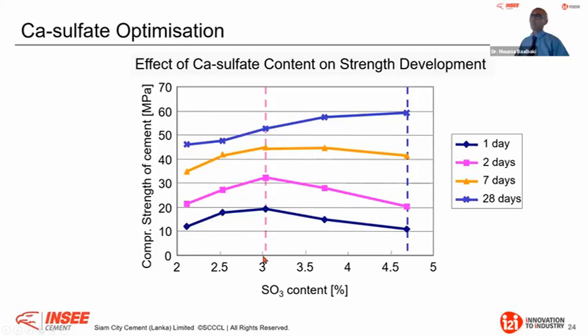But if we don't put enough sulfate, this could be okay for the 1 day strength, but you see the problem we have at 28 days is that because we start to produce what I call calcium aluminate hydrate, we don't have enough ettringite, and these are blocking. These are very strong retarders, let's put it like that, okay? They are somehow blocking the solution, okay, of the different species from the clinker to the solution that later on pay off in the compressive strength.